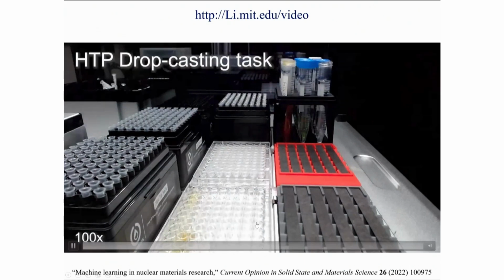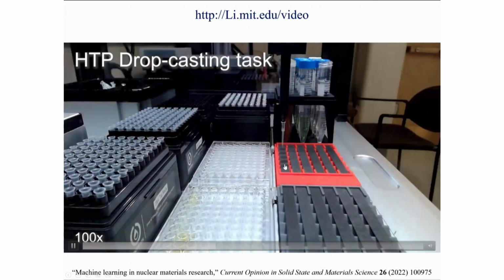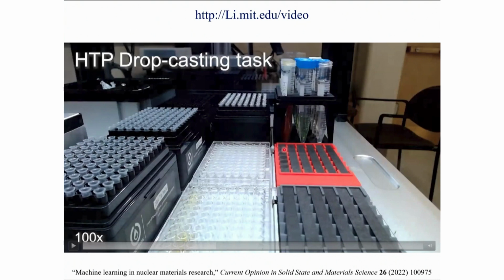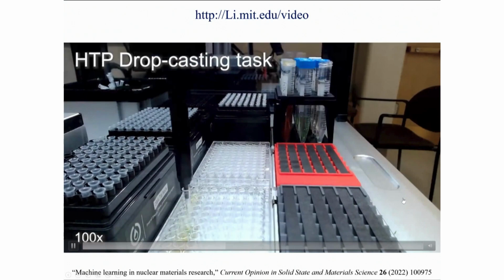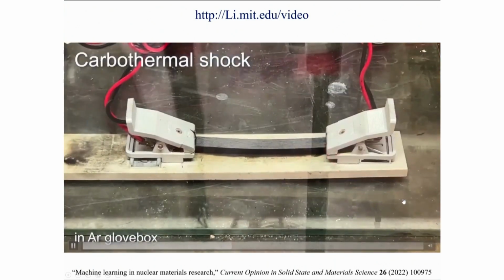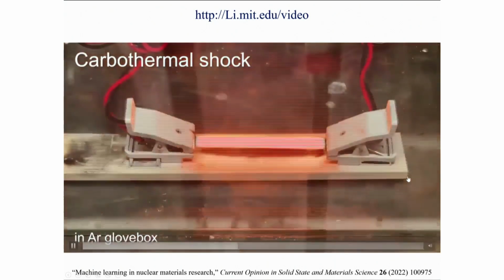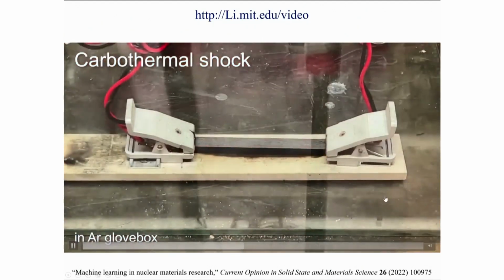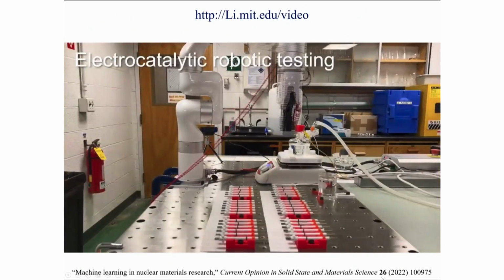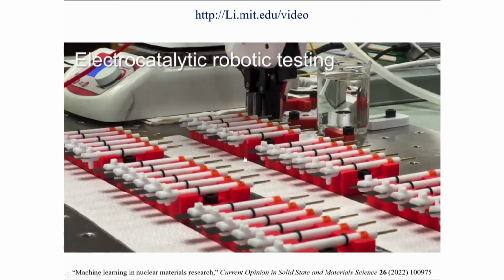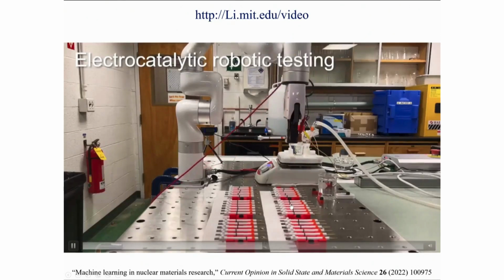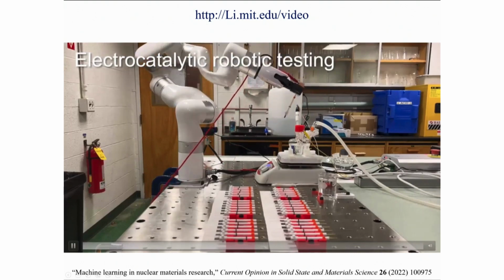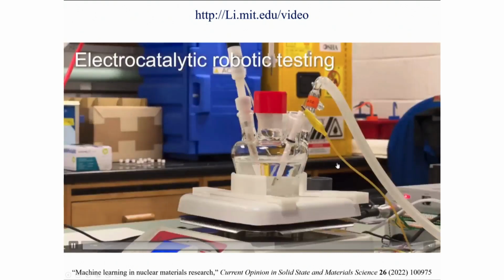And unlike traditional combinatorial chemistry, each of the compositions here is different. So it's not on a regular grid, but it's being proposed by the computer to be the best set of experiments to do. And then we perform this extreme processing in a few seconds, up to minutes. We can produce this high entropy alloy nanocatalyst. And then we load these onto carbon strips and then into this 3 electrode experiment.